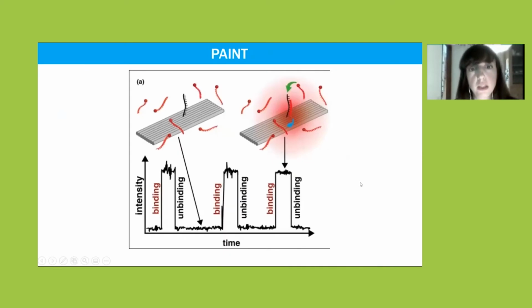Another way to have single molecule localization microscopy is the PAINT methods, that instead of relying on the photoswitching of dyes and this special buffer that we use, what they do is to label the structure of interest with an oligonucleotide. And then in the supernatant, you have the complementary one with a dye. Then every time that the complementary one binds to the structure of interest, then you have a blink in the microscope. So you are following these binding and unbinding events. And this is at the end what you will use to reconstruct your image.